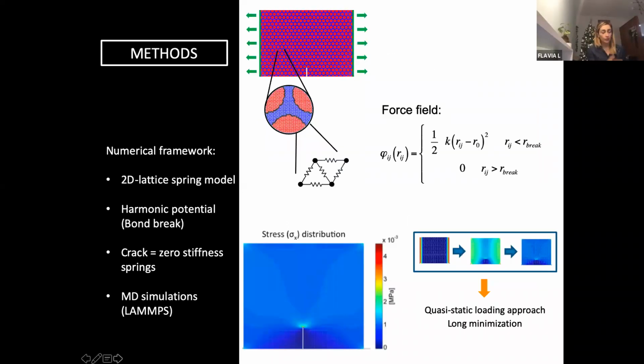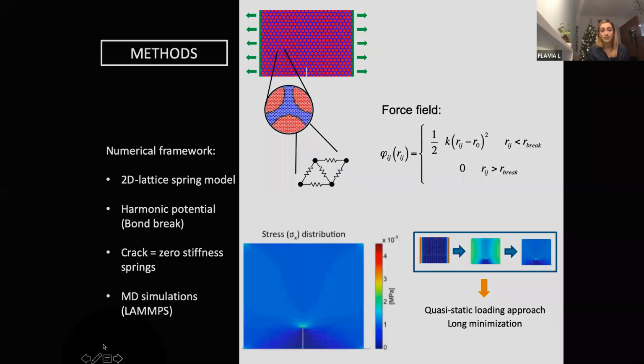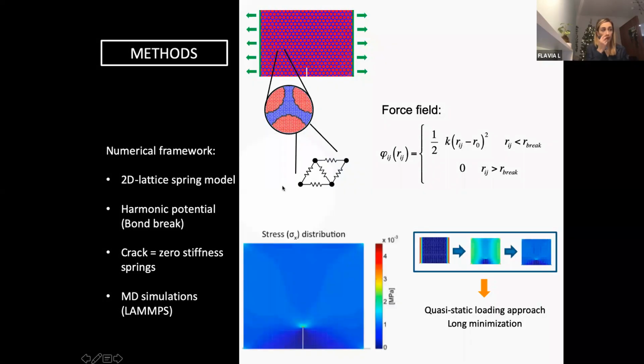So coming back to this lattice spring model, we implemented a 2D lattice spring model where we modeled the crack as a zero stiffness spring, and then we modeled the interaction of the beads through springs with a force field described by a harmonic potential. Of course, it's a simplified representation where we have only the elastic part, so we don't have plasticity in this model, but it's something that could be implemented afterwards.